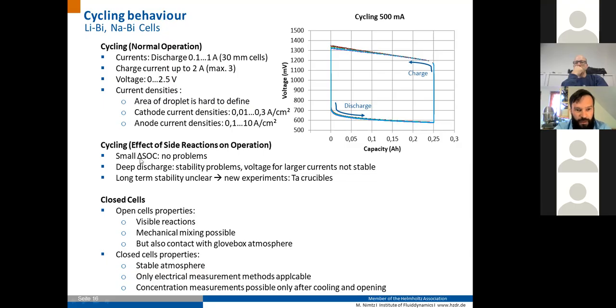Cycling with small delta SOCs, so this means small changes in the composition, showed no problems over longer times. For deep discharge, as I've shown here, there were often stability problems, and also for very large currents, the voltage was not stable, which meant that there were definitely some problems with the combination of the electrodes. Maybe the electrolyte layer was too shallow. We then switched to tantalum crucibles to avoid influences from the copper and iron crucibles, and the final step is to use closed cells to avoid reaction with the glove box atmosphere.